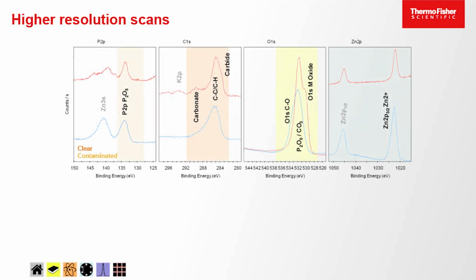We can look at the other ones as well. We can see the phosphorus is phosphate. We can see in the carbon contamination, we have a little bit of carbonate. There's a little bit of potassium there as well. And the oxygen, there's a couple of chemical states for the metal oxides and the carbonate and phosphate. And for the zinc, we've already established it's in zinc 2+.